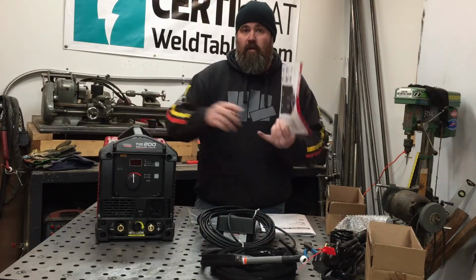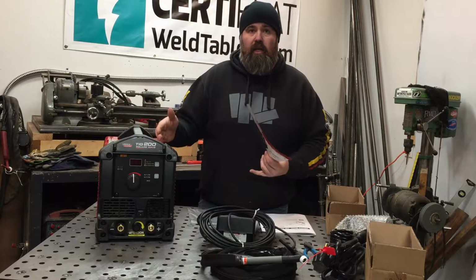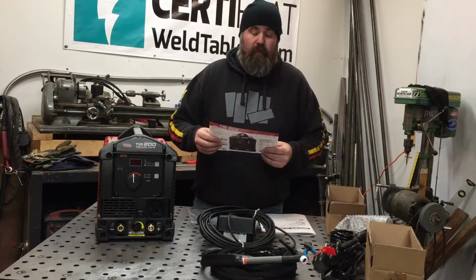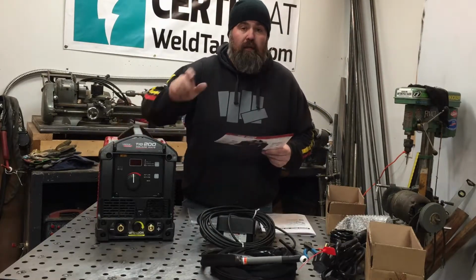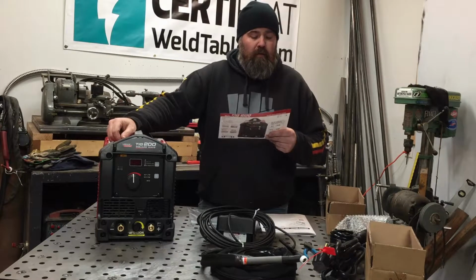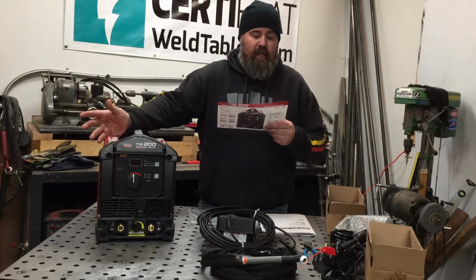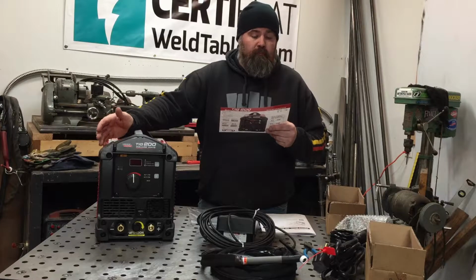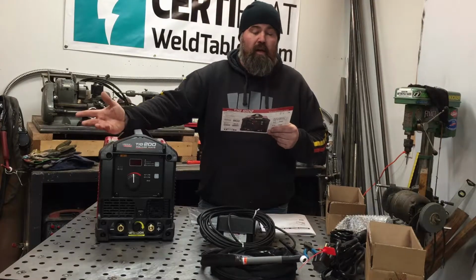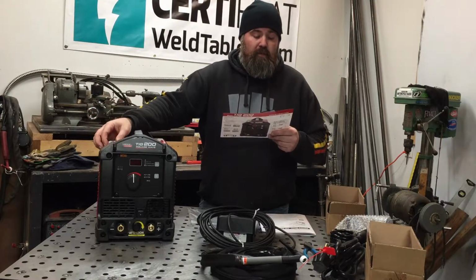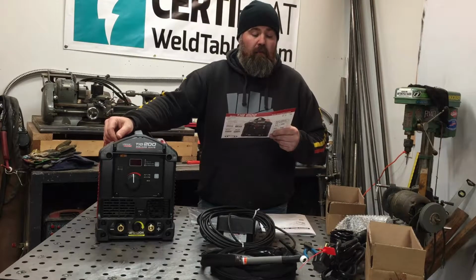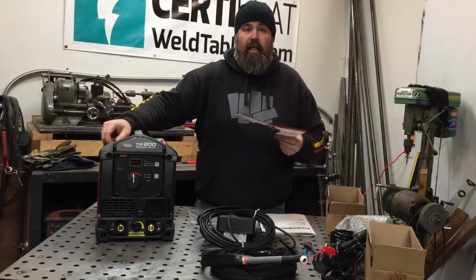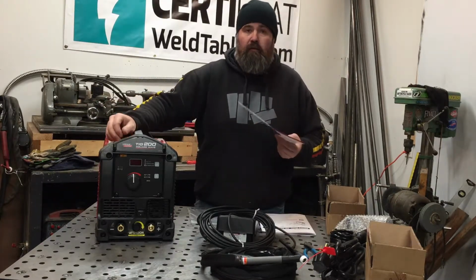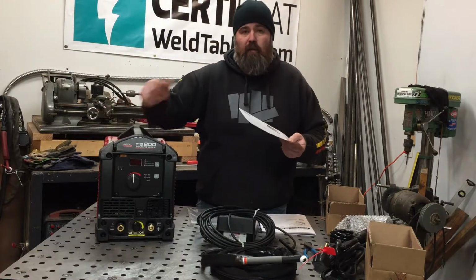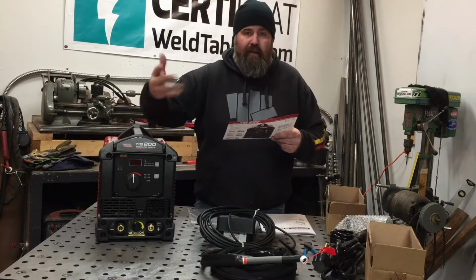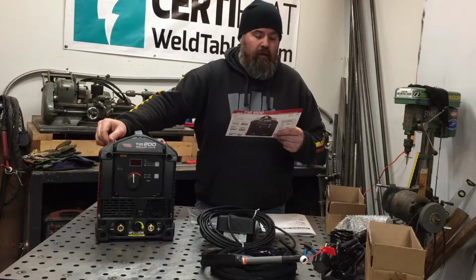Depending on you as the welder, the machine, and the quality of the material you're welding, you may need to adjust that up or down. They say for 16 gauge, 60 thousandths of an inch, they recommend 70 to 85 amps. Fair enough. If we set the machine to 60 and we go to strike an arc and it's not penetrating, obviously we'd want to turn it up. But that rule of thumb gets you in the ballpark.